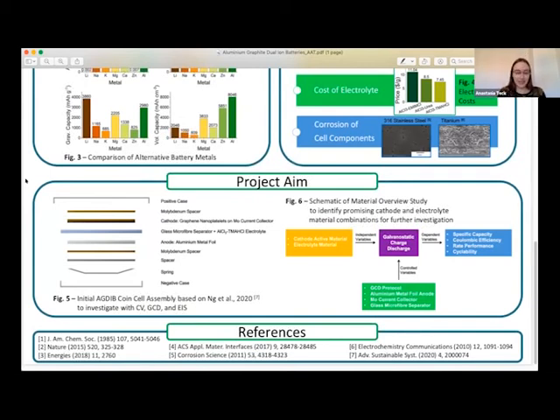So once I've succeeded in making this first AGDIB and have played around with it a little bit, I will move on to a material overview study where I will use various cathode and electrolyte material combinations, and will test them using only galvanostatic charge discharge to obtain data on capacity, coulombic efficiency, rate performance, and cyclability, while keeping all other parameters the same, to identify the most promising materials, which I will then further investigate to understand why they have good performance and to add to the known required specifications for AGDIB materials.